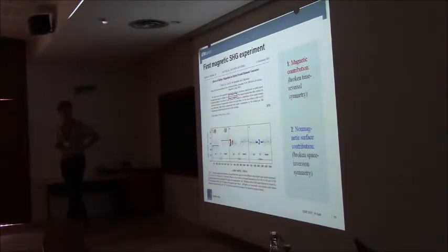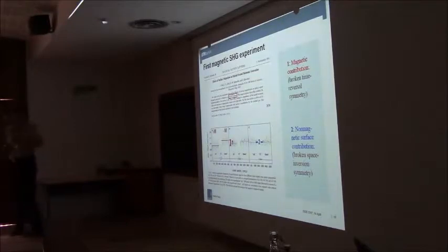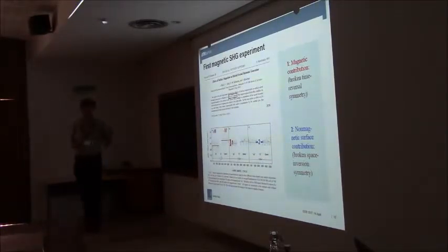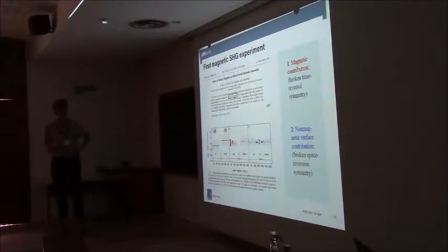So this is the first experiment where someone used it, not just for generating frequency doubling, but for really imaging or detecting magnetism. It's second harmonic generation on iron. Iron is ferromagnetic. So what did they do? They just measured the second harmonic emission for plus and minus magnetization generated in the iron, and you see there is a small splitting.